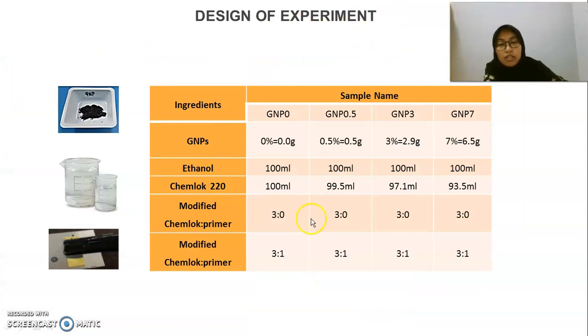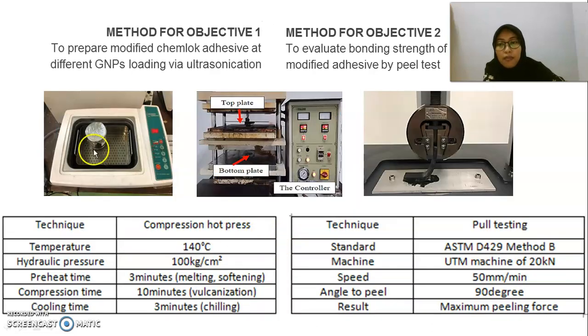This is the design of experiment. Basically, it has 8 samples, which are GNP 0 as a control and different weight percentages of GNP: 0.5, 3, and 7. The ratio we will use is 3 to 0 for the first 4 samples and 3 to 1 layer ratio for the other 4 samples. Next, the method for objective 1 to prepare modified Chemlock adhesive is by ultrasonication in ethanol in a beaker, then proceed to hot press compression at 140 degrees C for 10 minutes before the peel test to achieve objective 2.